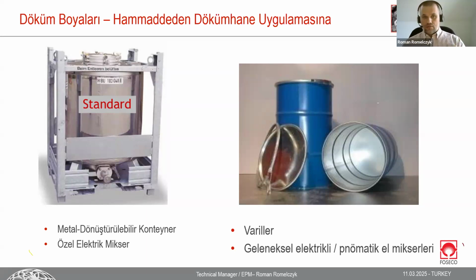When we talk about the left side of the slide, stainless steel containers with dedicated mixers. Currently, we can say this is the best solution to be sure that everything is fine with the coating during storage, but also during usage, because you can put a dedicated special mixer through the lid of the container and mix properly, because the mixer is designed especially for containers of this shape. It's also possible to have a timer, so you don't need to take care of the mixing time, the timer will do it by itself. So you can be sure that whenever you use a coating, it's ready to use.